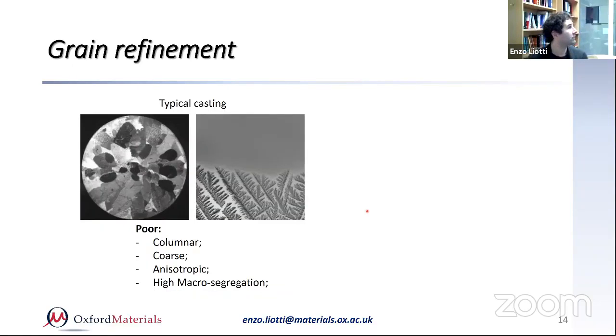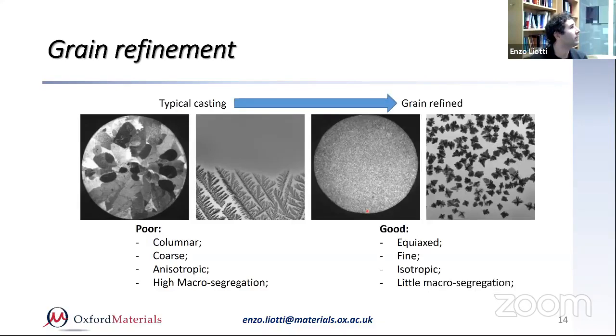A typical casting has a coarse, columnar, anisotropic microstructure, and we normally retain high macrosegregation. That's what happens if you try to cast a component and you don't do anything. If you just pour the liquid metal, the columnar microstructure tends to be favored. What you really want to obtain is a grain refined microstructure, so an equiaxed, fine, isotropic microstructure. We retain little macrosegregation and it looks like this. This is a macro scale, and this is actually the small dendrite, right?